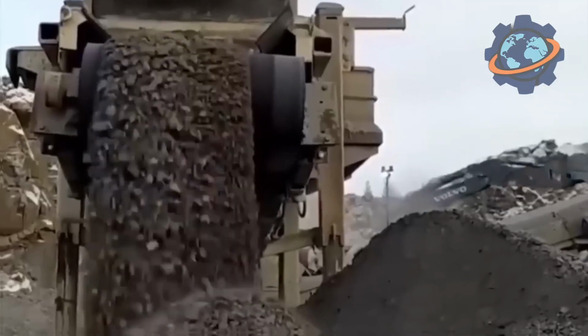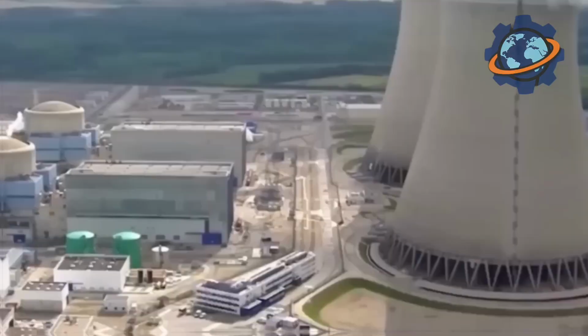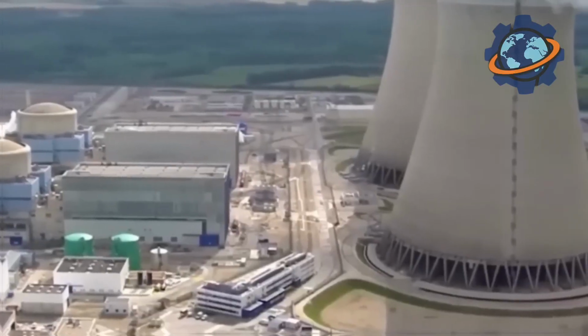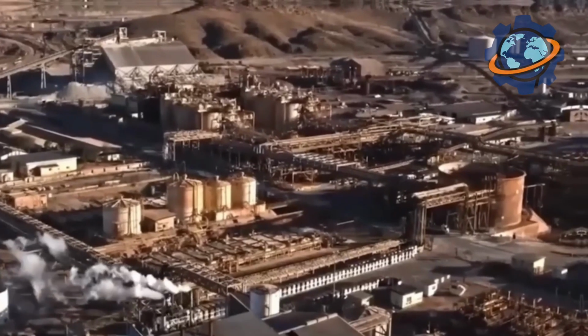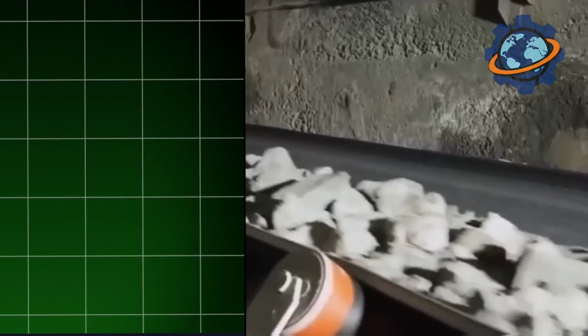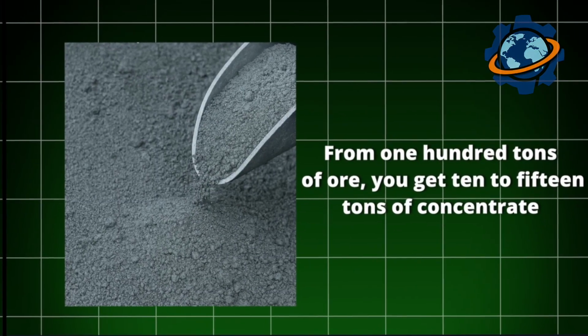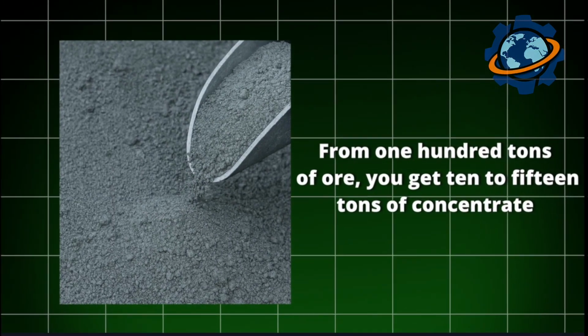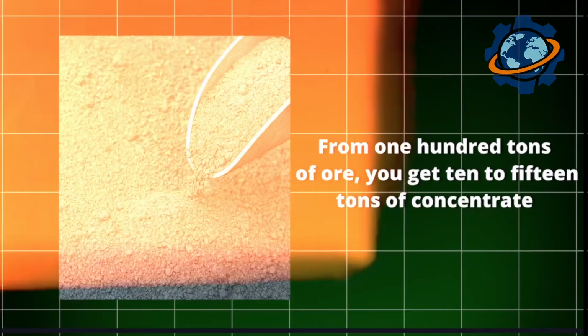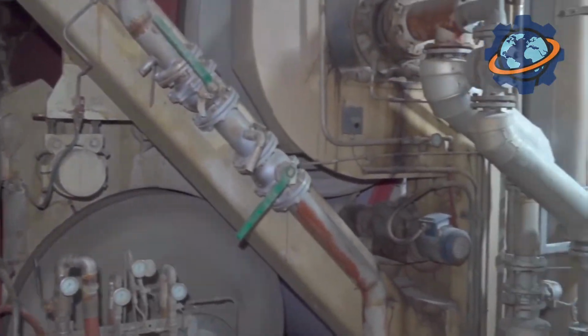The foam is collected, filtered, dried. The result is concentrate, powder containing 50 to 60% zinc. From 100 tons of ore, you get 10 to 15 tons of concentrate. This concentrate is loaded into rail cars and shipped to the smelting plant.